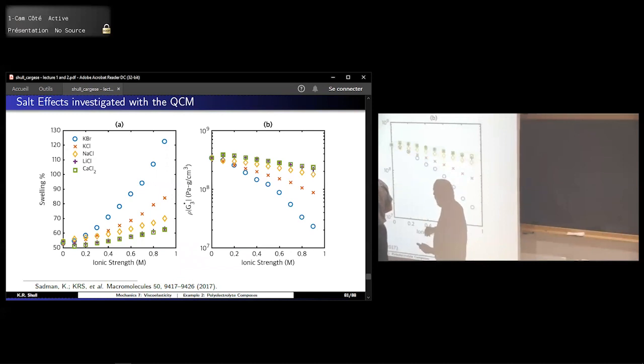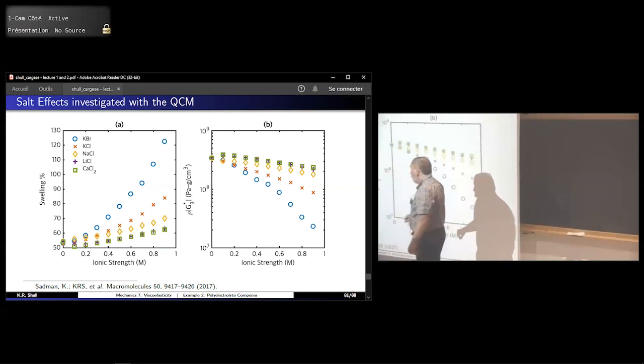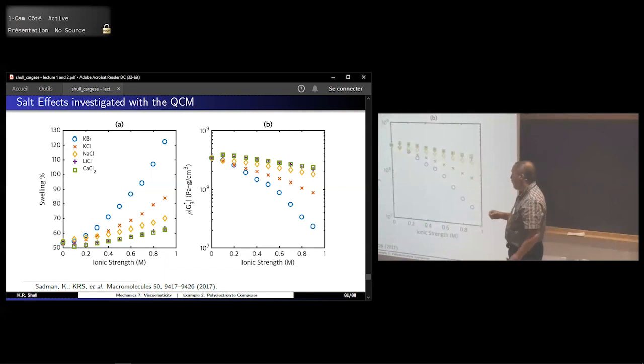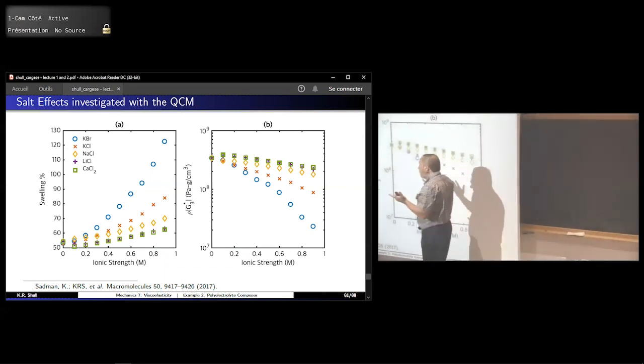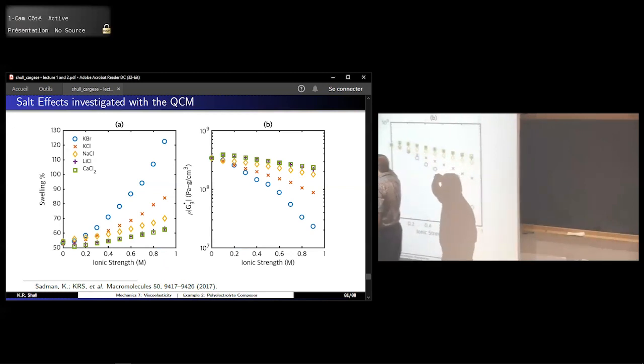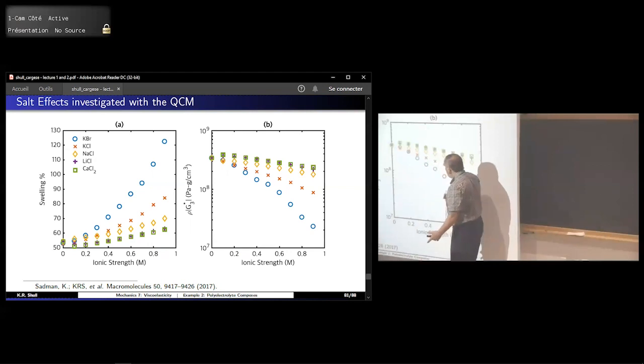From the shift of the phase, how do you know how much of it is swollen polymer versus solvent? Well, that's a pretty easy problem to solve. It's a two-layer model. You're measuring the solvent itself on top of the film, and you're pretty sensitive to the separation. Which part of your measurement are you using, the inertia part or the dissipation part? It's not a direct additive measure. You basically have to have a two-layer model and fit to that to see what's really going on. But it works pretty well.